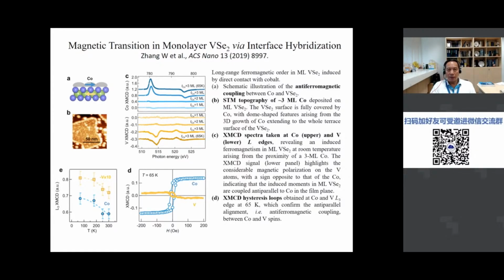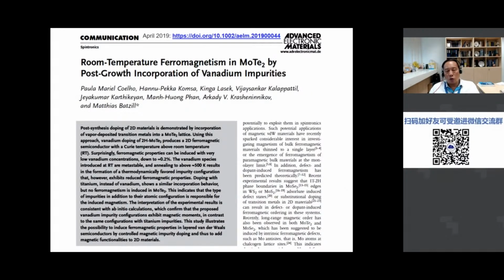But other people have also observed that you can make non-magnetic TMDs magnetic by doping, which is another method, of course. Of course, doping of a 2D material is a little bit more challenging. You're basically substituting atoms within the one layer. And in this case, the Batzel group, again in Florida, managed to make molybdenum ditelluride magnetic by incorporating vanadium impurities. So this work suggests that such impurities could make a non-magnetic TMD magnetic, which also then raises questions about whether it was impurities that caused the initial vanadium diselenide work in Nature Nanotechnology to induce the magnetism there.